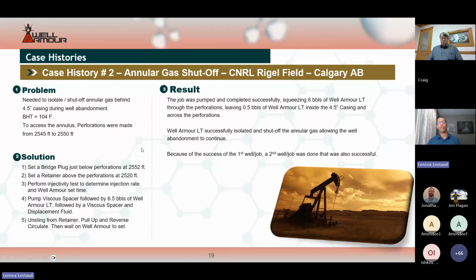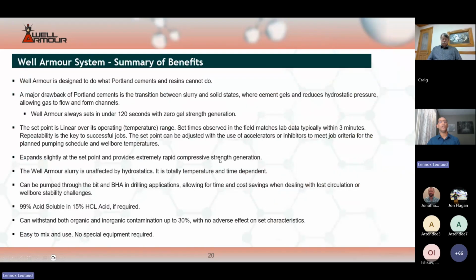Here's a second case history in which Well Armour was used to shut off annular gas on a CNRL well in Calgary. During well abandonment, the operator needed to shut off annular gas behind the 4.5-inch casing. For this case, squeezing through a retainer, a total of 6.5 barrels of Well Armour LT was pumped, of which 6 barrels was squeezed through perforations at 2545 to 2550 feet, and 0.5 barrels of Well Armour was left in the 4.5-inch casing. The application of Well Armour was able to completely shut off the annular gas, allowing the well abandonment operation to continue.